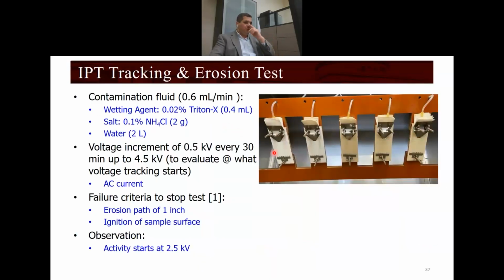And this is the IPT test. For those samples, we're still working on them, of course, but we did some screening. This is a screening test, basically. It's not like the samples I presented before for the different molecular weights, which were fixed at 4.5 kilovolt until failure happens. In this case, we increment by 0.5 kilovolt every 30 minutes. This is to evaluate what happens to the voltage, to understand at which voltage exactly the tracking starts to happen.